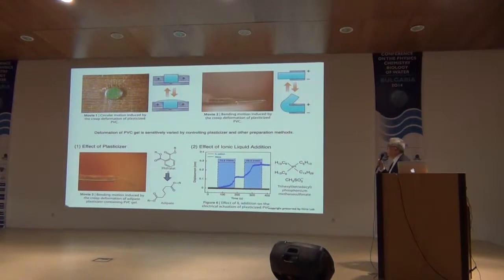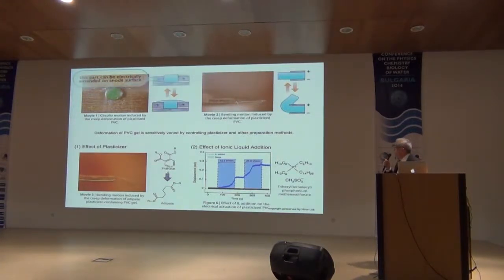But to utilize this kind of deformation for practical use, I use this kind of electrode alignment. This is the cathode, and here is the gel. Then we apply an electric field. With this kind of deformation, the gel creeps out onto the anode surface. And when we employ this kind of alignment, the gel bends in this way.